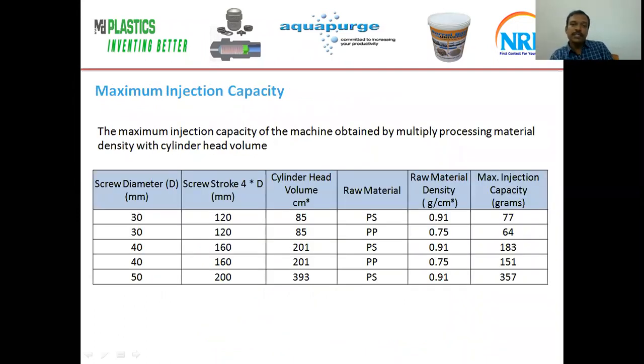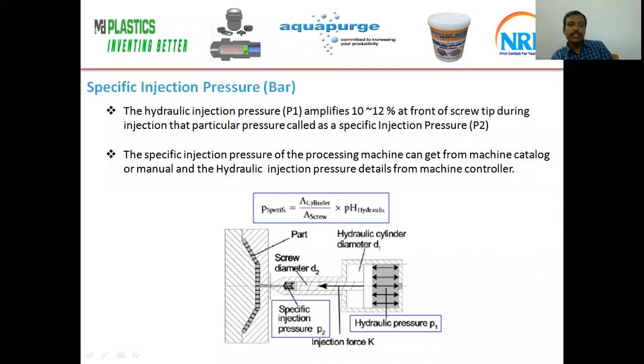The maximum injection capacity of the machine can be arrived at by multiplying the processing material density with the cylinder head volume. See, if you take the example of a 50 diameter screw, the cylinder head volume is 393. If you process PS material, the maximum injection capacity might be 357 grams. If you change to PP, the PP density is to be multiplied with the cylinder head volume. Specific injection pressure.